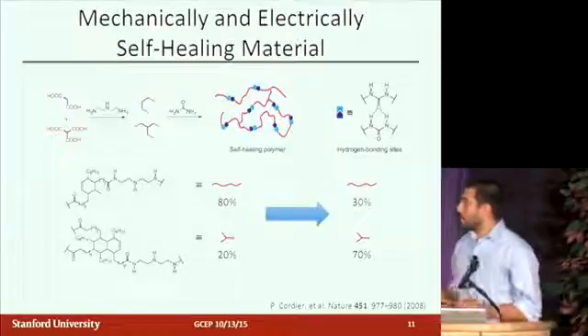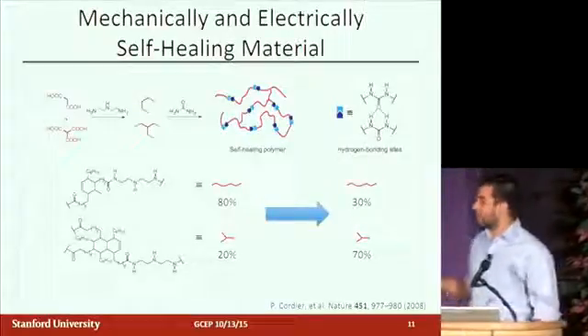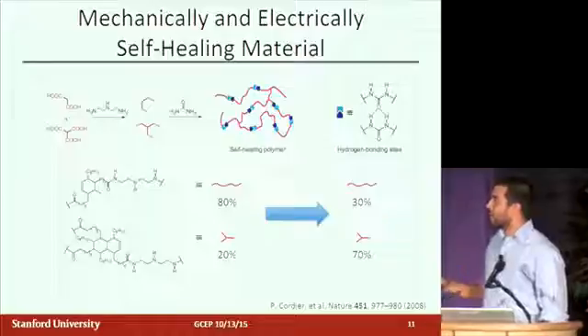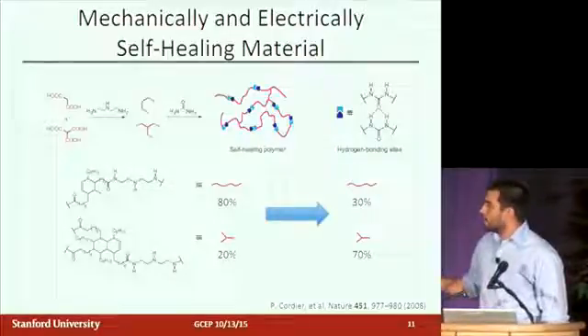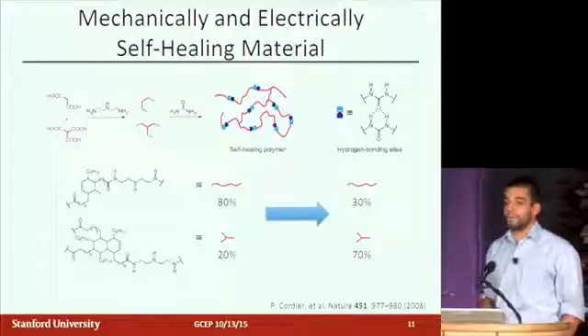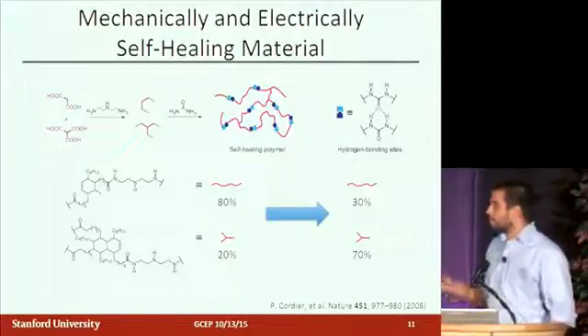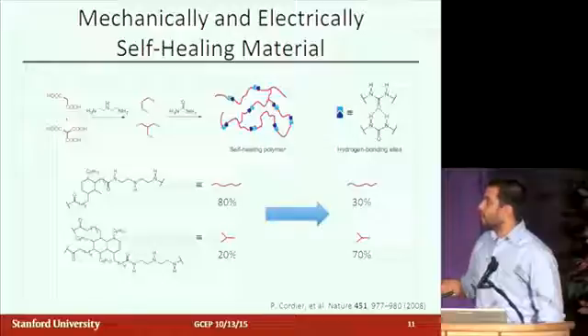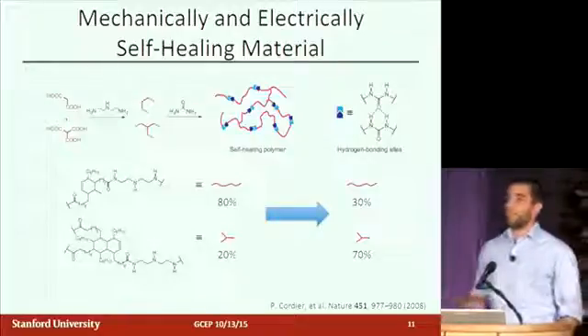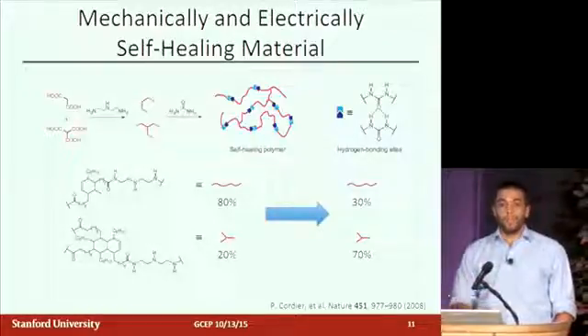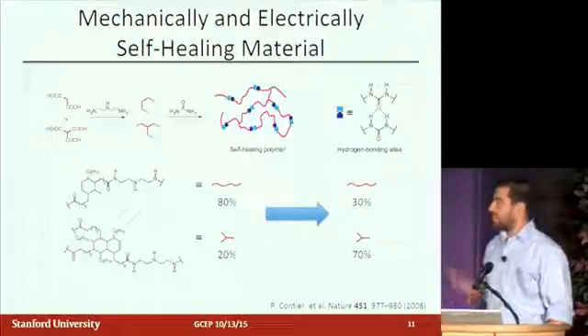If you're interested in the chemistry of the self-healing polymer, it's here. We start with a diacid and a triacid fatty acid material, so they're actually derived from vegetable oil. They're quite cheap as well. We functionalize them with amine, and then functionalize them again with a urea to give us that hydrogen bonding that allows us to have the supramolecular self-healing capabilities that we think help it do so well in the batteries.